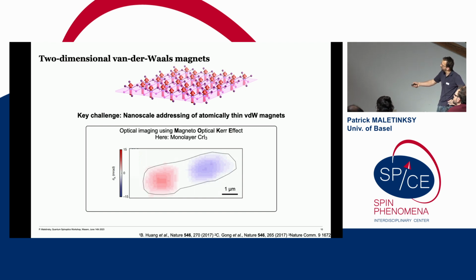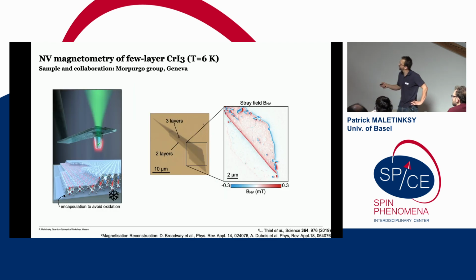And here you see an example of one of these first compounds that was discovered, chromium triiodide. Here you see such a flake that breaks up into two domains, signaled by these red and blue patches. You see that one can image this magnetism, but of course with much reduced spatial resolution. And also not all van der Waals magnets are Kerr active and can be addressed using this technique. This is what motivated us back then, roughly in 2018, to go into this field. For this, we collaborated with my colleague Alberto Morpurgo from Geneva, who provided us with first samples, and we started exactly with that compound, chromium triiodide.